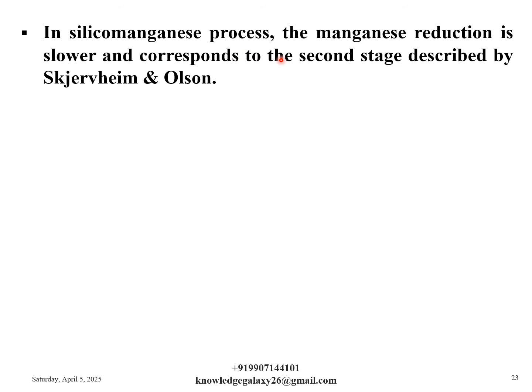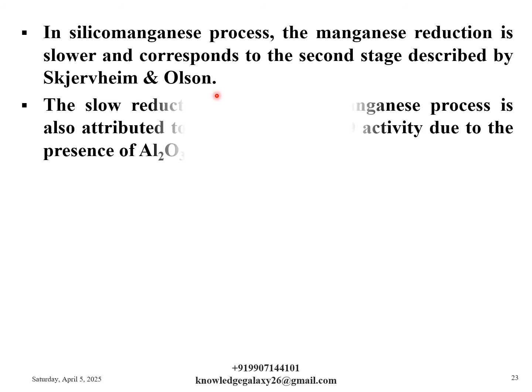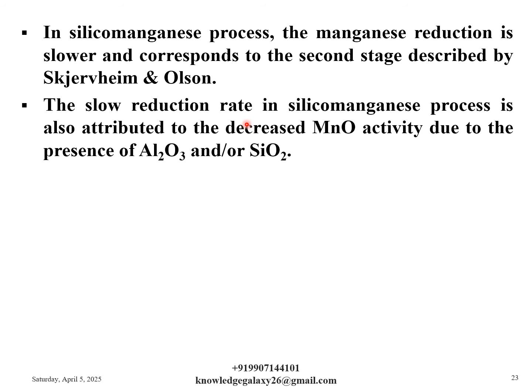In the silicomanganese process, the manganese reduction is slower and corresponds to the second stage described by Skjervheim & Olson. The slow reduction rate in the silicomanganese process is also attributed to the decreased MnO activity due to the presence of Al2O3 and or SiO2.